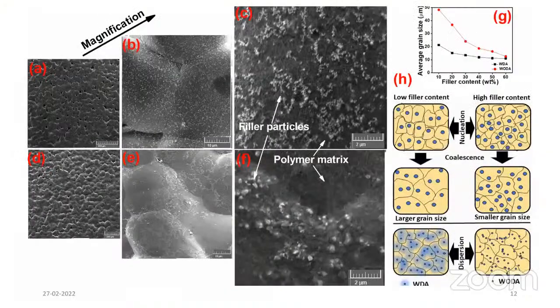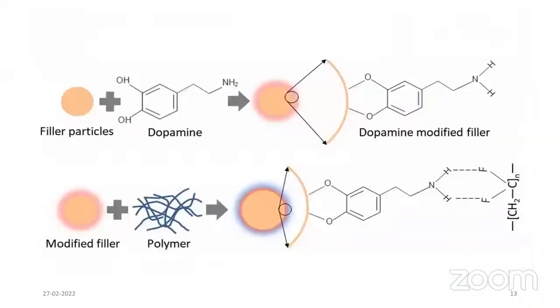Then this is the FE-SEM analysis. A, B, C are the images with dopamine added, and D, E, F are the images of the samples in which dopamine was not added. These images are of 10%. I concluded that low filler content gave larger grain size and high filler content gave smaller grain size. And this was the chemical equation.